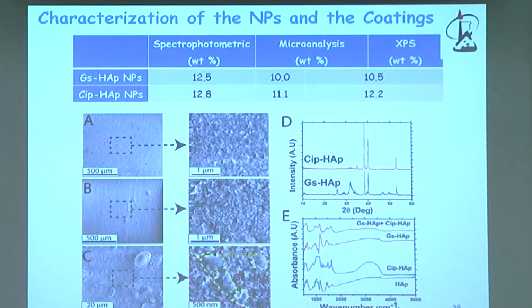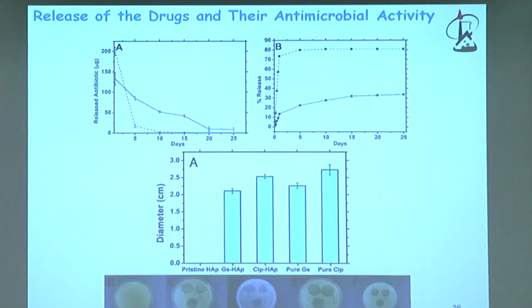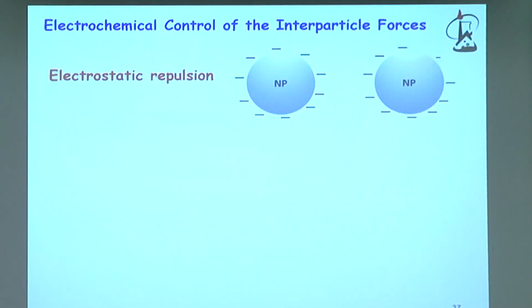Here there is the analysis by three different independent methods of how much antibiotic we have in this hydroxyapatite. You can see it varies between 10 to 12%. And again, everything is shown here, the deposition, and we characterize the deposition and so on, but I will skip that. We'll show just this case, that indeed the hydroxyapatite nanoparticles after deposition still have very clear antibiotic activity as compared to the hydroxyapatite which is not loaded with antibiotics. So this is one way.